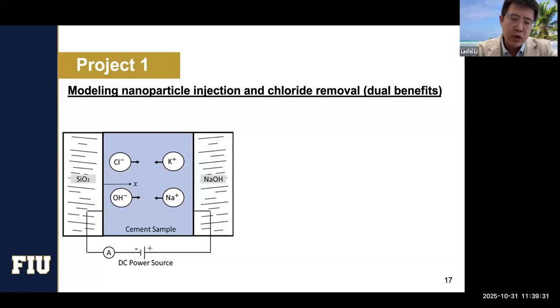After we finished the experimental work, we thought maybe we could do a little bit of modeling, which can save us a lot of time figuring out how to optimize the nanoparticle injection. So we started brainstorming how to model the nanoparticle injection process. At the same time, we thought there might be a possibility, because it's exactly the same setup as rapid chloride penetration and chloride removal. Once we inject the nanoparticles, we can also push the existing chloride ions out of the system, so we can have dual benefits.